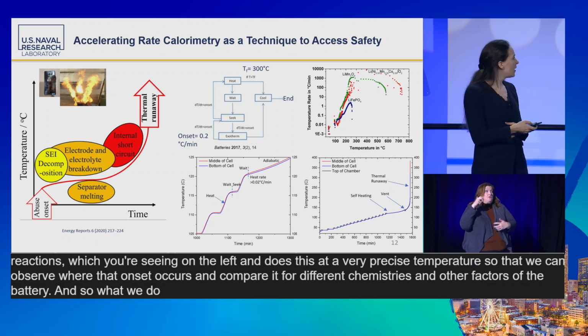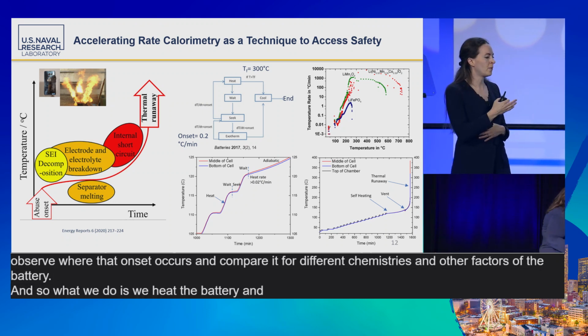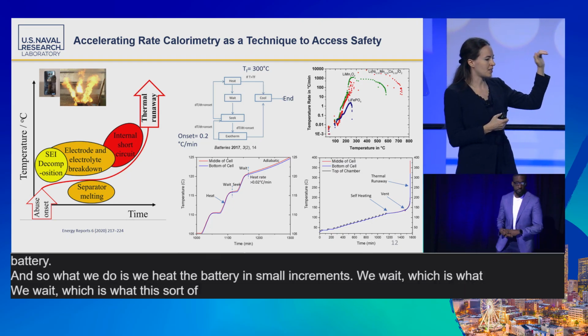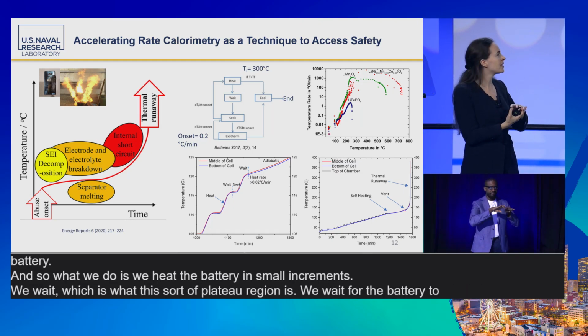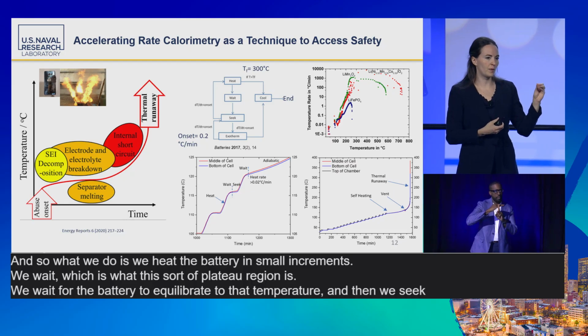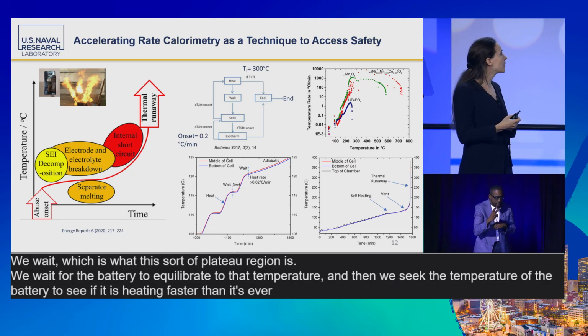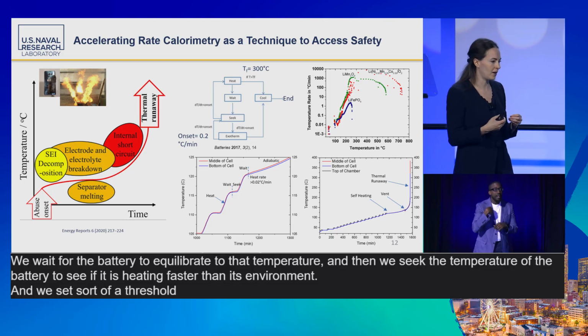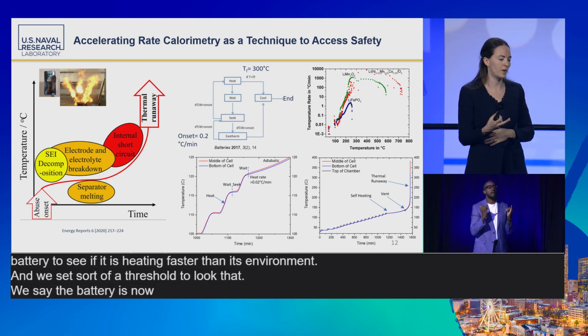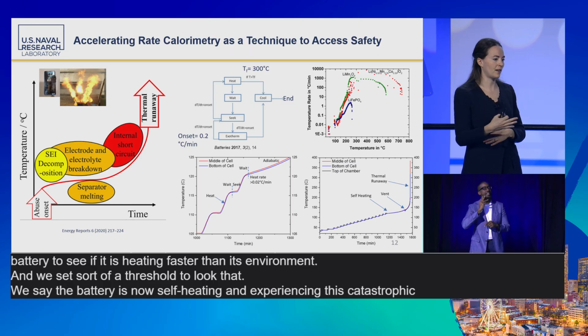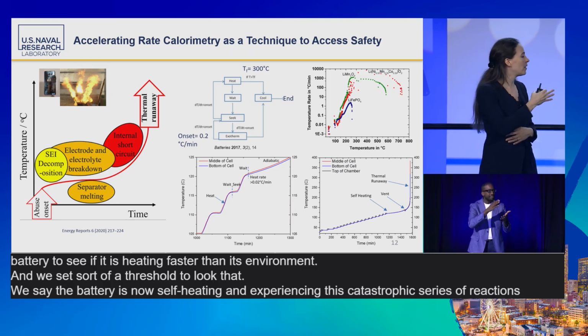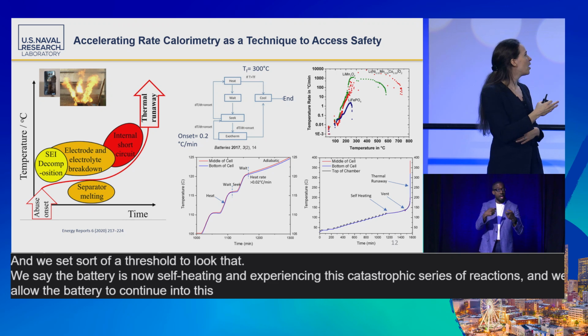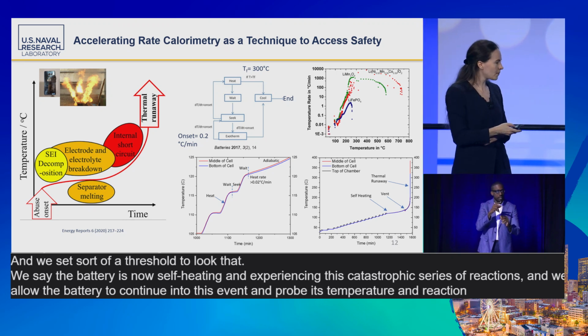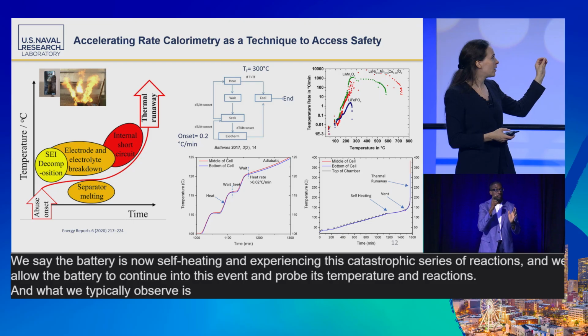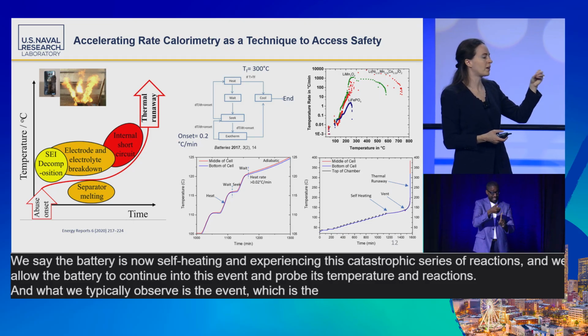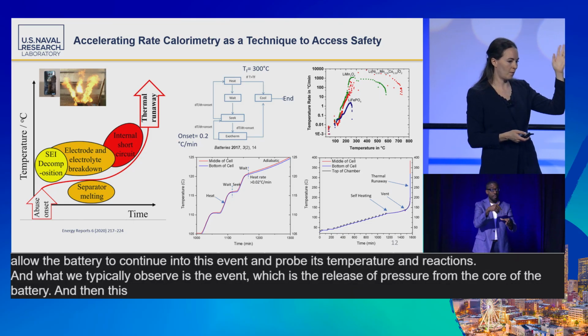And so what we do is we heat the battery in small increments. We wait, which is what this plateau region is. We wait for the battery to equilibrate to that temperature, and then we seek the temperature of the battery to see if it is heating faster than its environment. We set a threshold, and we say the battery is now self-heating and experiencing this catastrophic series of reactions. And we allow the battery to continue into this event and probe its temperature and reactions. What we typically observe is the event, which is the release of pressure from the core of the battery, and then this rapid thermal runaway.